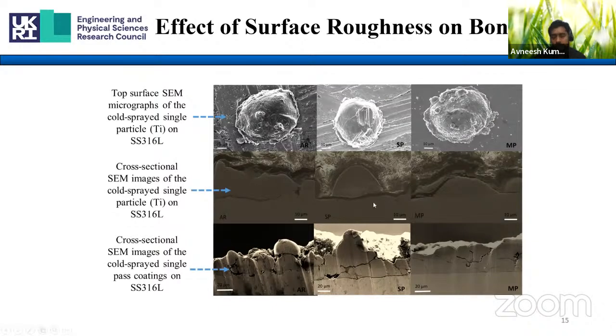So to further see which one is better, we analyzed the cross section of single layer cold sprayed coating. We have seen that in the as-received case, there were some voids between the particle and the valleys of the surface, and these voids influence the bonding in a negative way. In the semi-polished case, there was a thick crack or gap between the coating and substrate, which shows that there was no bonding. And in the mirror polished case, there was no gap or crack at the interface. So from here, we realized that mirror polished surfaces are good.